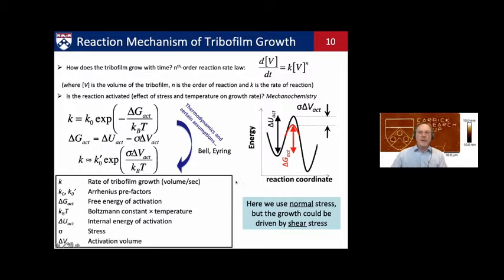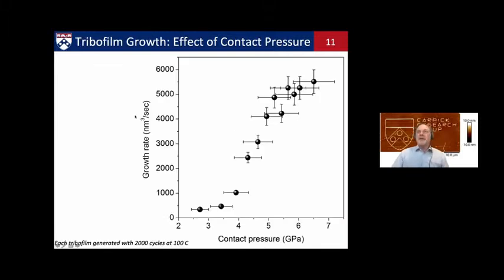Now, I'm going to talk about normal stress, but I want to point out, and I have a citation on another slide, that Hugh Spikes has done some nice work showing that shear stress is likely the driver in the case of ZDDP. Normal and shear are correlated in our sliding experiments, and so we think that what we're seeing here also are shear-related effects. So here is how that growth rate changes with the contact pressure.